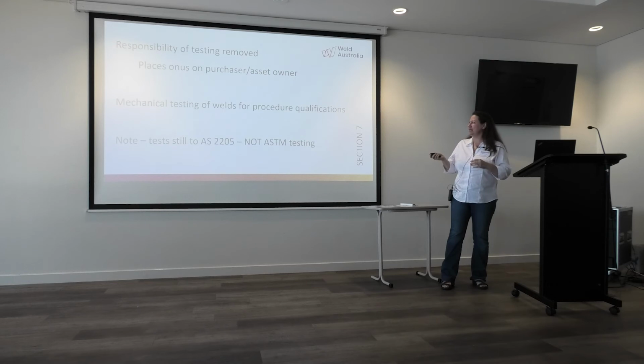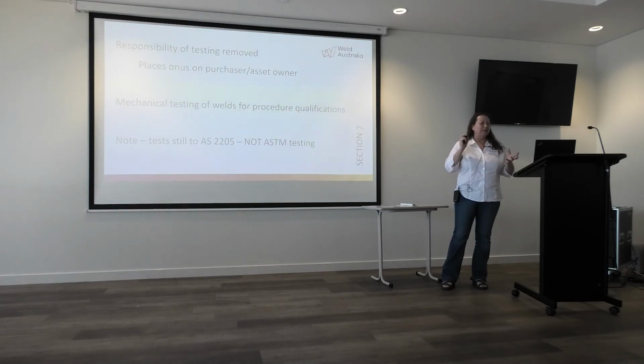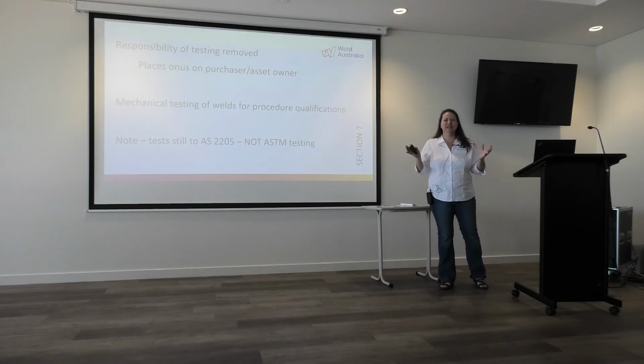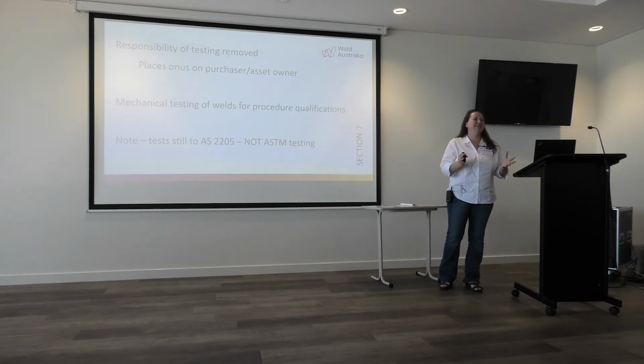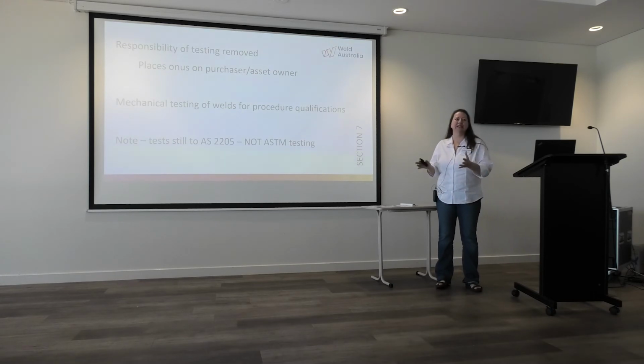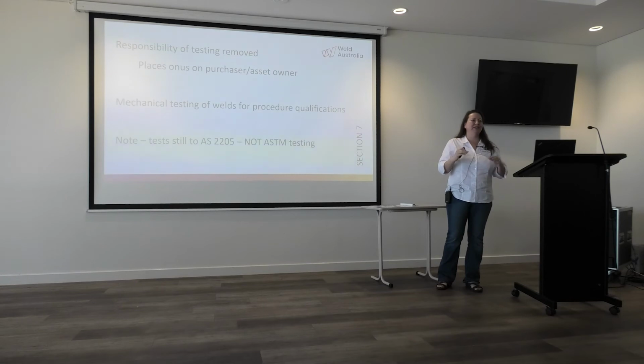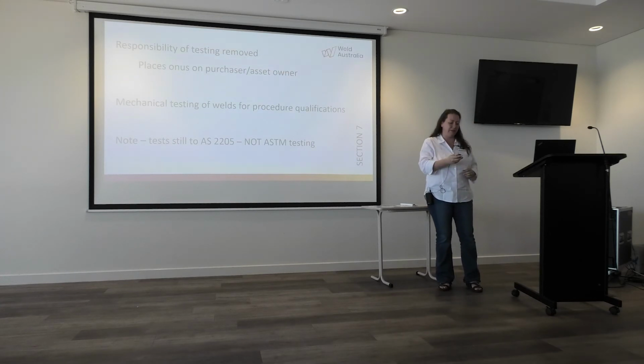And then mechanical testing for welding procedure qualification is actually to AS 2205. Now 2205 was on the list of standards to be cancelled because there weren't enough technical people to review them, so they just reconfirmed them. But all of our testing to 3992 should be to AS 2205 because that's the standard referenced, even though a lot of companies do testing to ASME. So you'll see testing to ASME for this, NDT to ASME. While that may be applicable, the standard still says 2205. And the thing to be noted is that 2205 is slowly being changed over to the ISO standards for testing. So not all the ASME testing stuff may be applicable going forward.